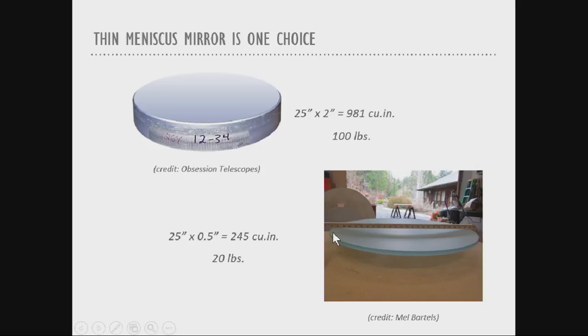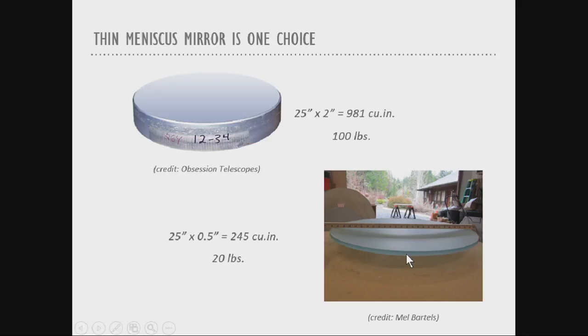Contrast that with a meniscus, which is pictured here. This is a 25-inch meniscus created by someone called Mel Bartels, who's really one of the vanguards of this whole thrust of using thin meniscus mirrors, and he's one of my mentors and helping me out. So this is his 25-inch, which he recently completed. It just came back from the aluminizing, and you can see here it's 25 inches in diameter and it's 1/2 of an inch thick. And so if you just do the math, this is 20 pounds of glass. So this is 1/5 the size of this mirror. So just from a sheer weight perspective, this is hands down going to be far more portable than your traditional glass.